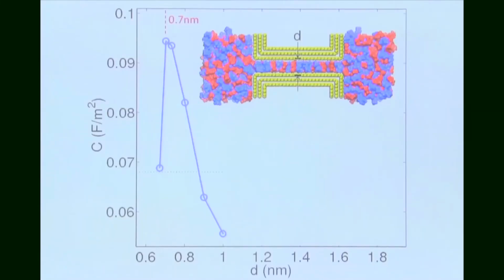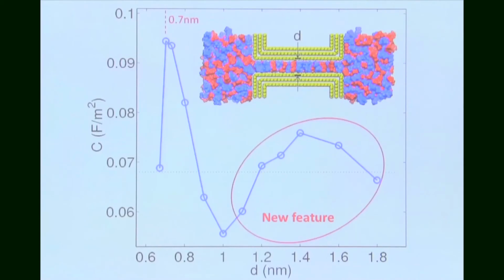As shown in this graph of capacitance versus pore size, we can see that as the pore size decreases from 1 nanometer, the capacitance increases and reaches a maximum at 0.7 nanometer, and then decreases. This capacitance behavior agrees very well with experimental results. As the pore size increases from 1 to 1.8 nanometer, a second peak occurs, which is a new feature revealed by molecular dynamics simulation for the first time.